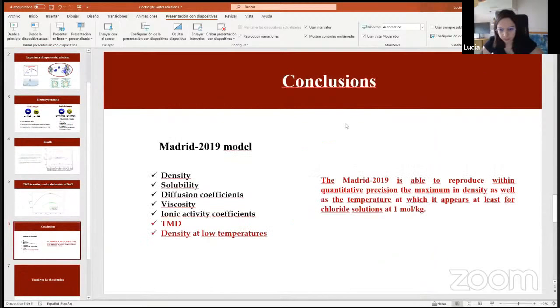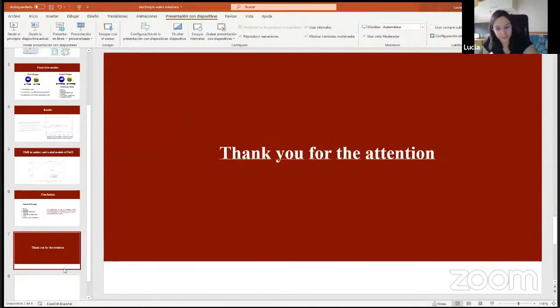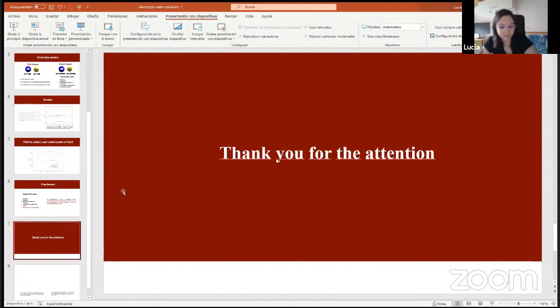So the conclusions are that the Madrid 2019 model is able to reproduce with quantitative precision the maximum in density as well as the temperature at which it appears, at least for sodium chloride solutions at 1 molal. So we can add these two properties to the properties that the model improves. And that is all. Thank you.